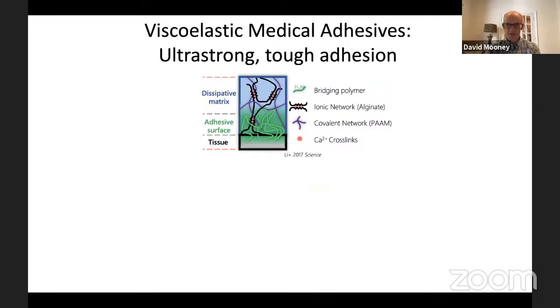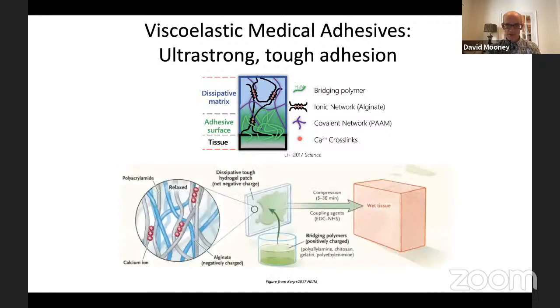And they specifically proposed to use chitosan that could form entanglements, ionic interactions, and also covalent linkages between the two. The basic idea is we'd have our gel, we would coat it with a chitosan solution, place it in contact with the tissue for a short period of time, allow adhesion to occur, and now have a material that would conform to the underlying tissue, be capable of dissipating significant stresses as it moved and flexed in response to loading from the tissue itself.